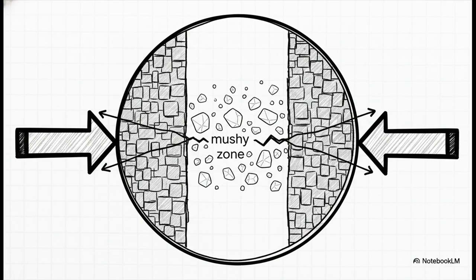So this massive shrinkage puts the cooling weld under incredible tension. And for a lot of aluminum alloys, there's this wide temperature window where the metal's kind of slushy. It's not quite liquid, not quite solid. That mushy zone is super weak, and the stress from the shrinkage can literally pull the weld apart, creating tiny cracks right down the middle. They call it hot cracking, and it's a disaster for the strength of the joint.